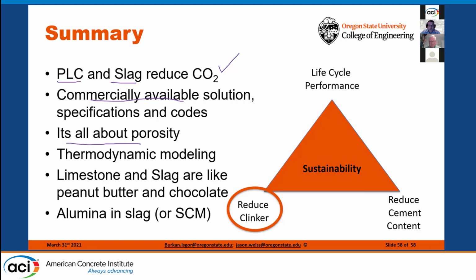And what we've shown is a thermodynamic modeling tool that really builds on things that have been in the concrete industry for 80 years, but it takes them from OPC to really start considering PLC, slag, fly ash, silica fume, right? Limestone and slag are really like the peanut butter and chocolate, right? On their own, they're good, but when you put them together, you get that peanut butter cup that's really the overall beneficial system. And it's really the alumina that's in the slag that gives you that bang for the buck, and that's really what you're after.